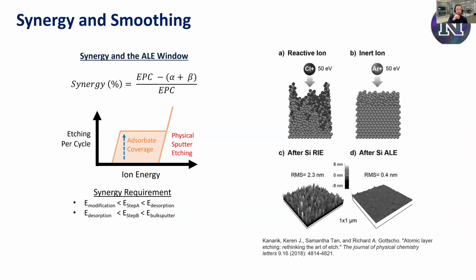This has been shown over and over again to smooth surfaces. You can see a really nice example that Lam published, I guess, gosh, 8 years ago now, where on silicon-chlorine, that canonical process, they show that with the RIE process, they get a surface roughness afterwards of 2.3 nanometers. When they use an ALE process, that's much reduced.